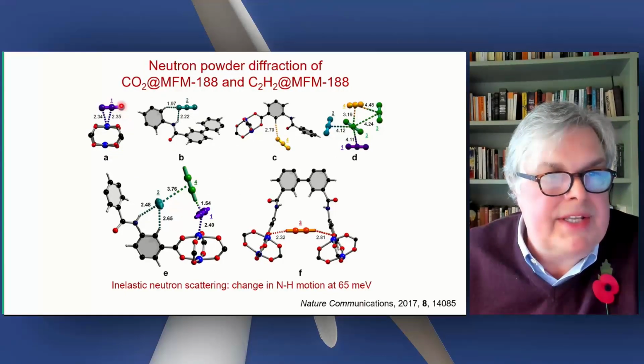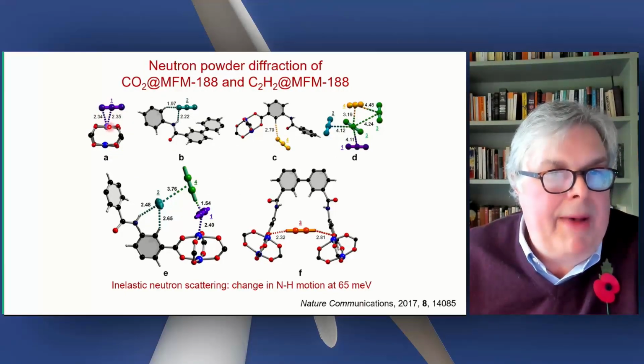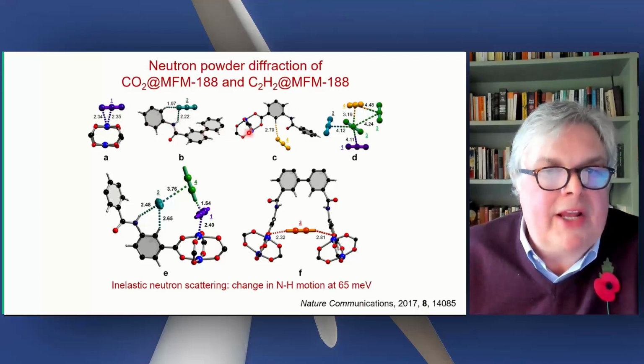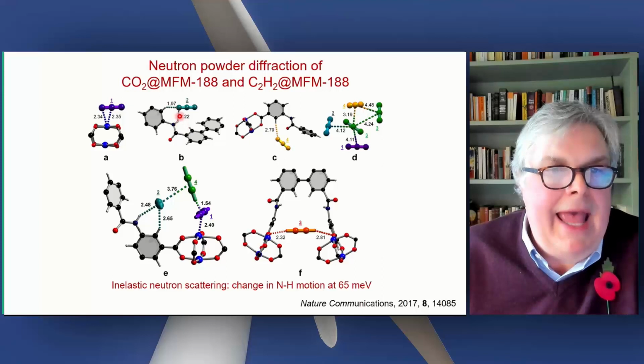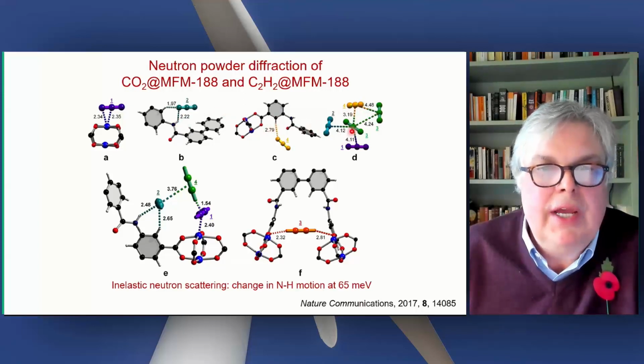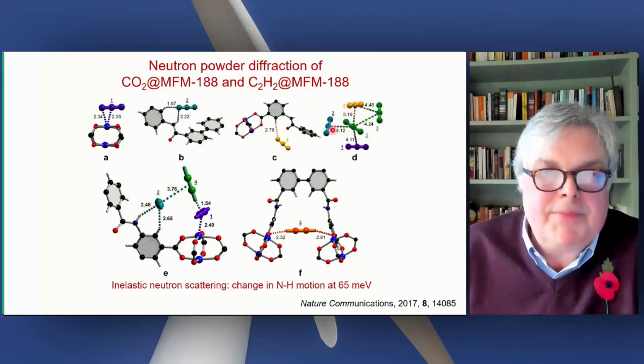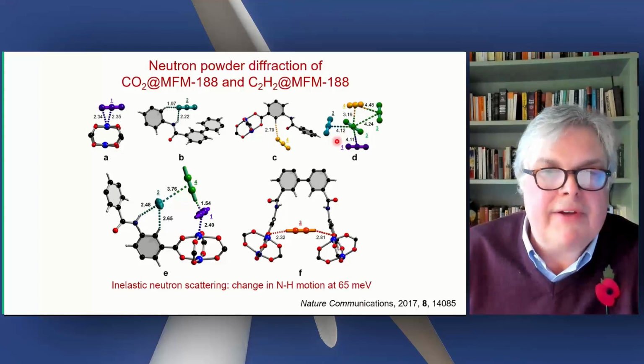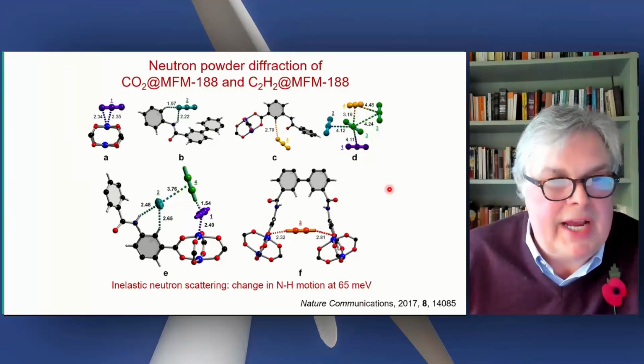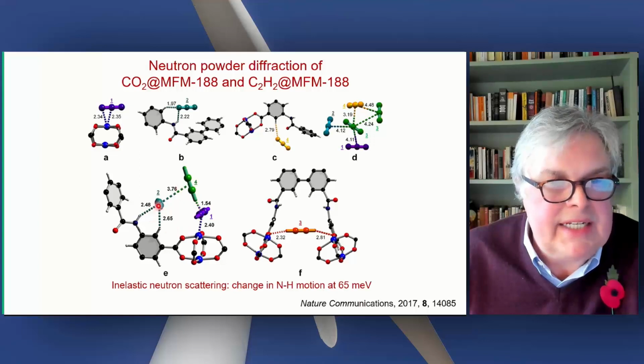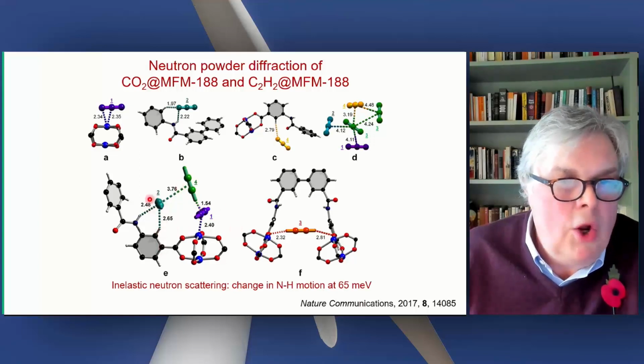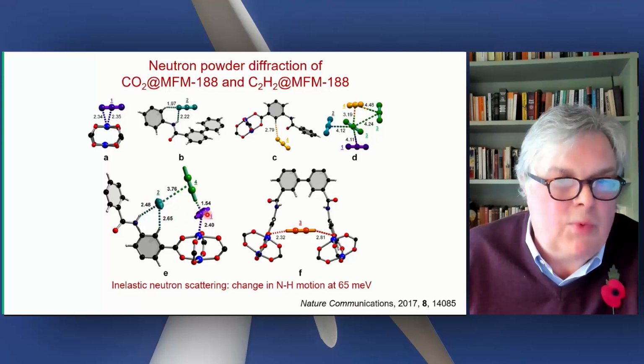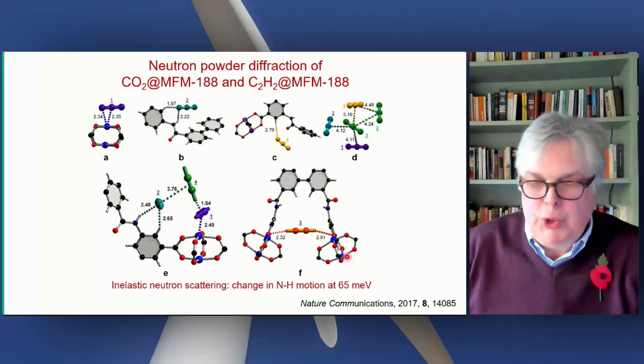Here is the CO2 interacting with the paddle wheel. Importantly, and very commonly, we see supramolecular NH and CH interactions, and also interactions with the substrate itself. So the packing of the substrate is on occasion a real driving force for the substrate to go into the channels. Here are the binding sites for acetylene, and you can see an element of cooperativity. Once this site coordinates and this one binds, then this is a very nice site now for the fourth acetylene to come in to interact with number 1 and with number 2.